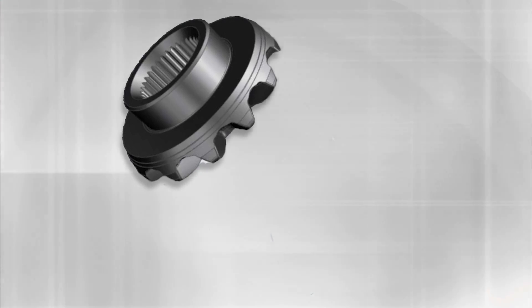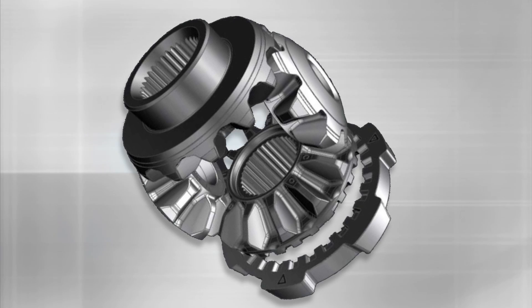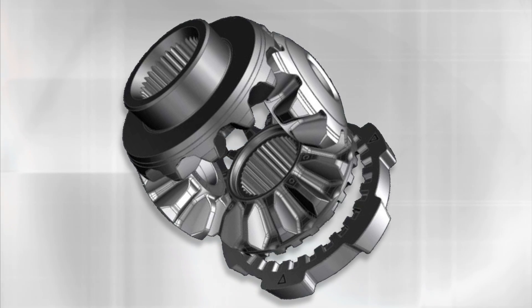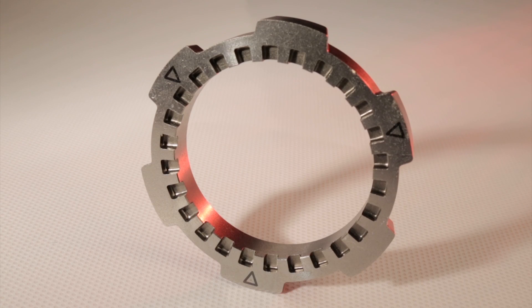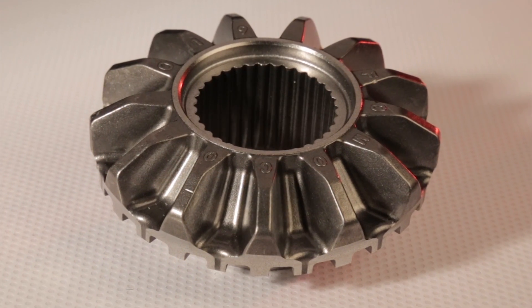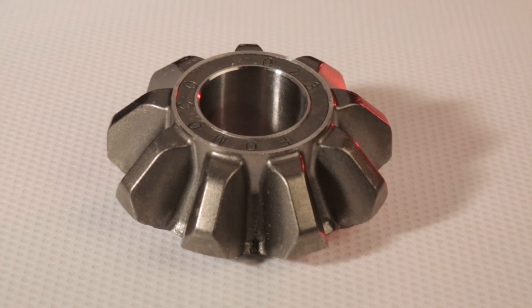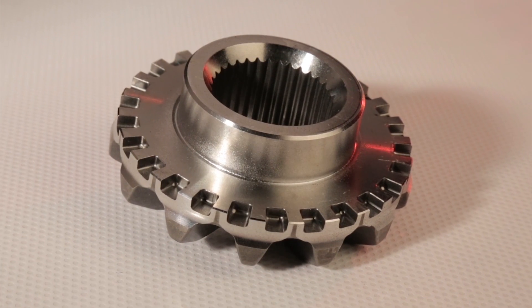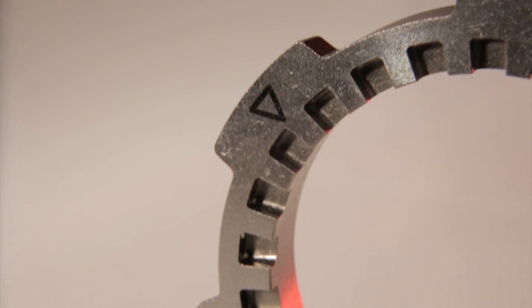All five components are made of low-alloy steel, produced to a minimum density of 7.80 grams per cubic centimeter, and delivered in the carburized, quenched, and tempered condition. Net-shaped forging yields the external cam teeth on the locking plate, side gears with AGMA Class 6 internal splines, pinions with AGMA Class 7 bevel gear teeth, and dog teeth on both locking parts that are held to a 0.2 millimeter profile tolerance.